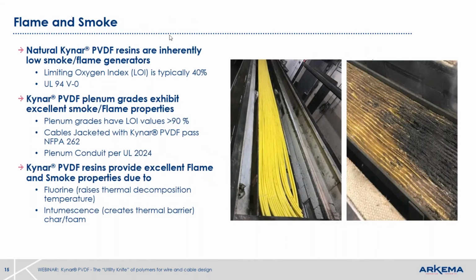Smoke and flame resistance. PVDF is inherently smoke and flame resistant. The limiting oxygen index value for unadulterated PVDF is around 40. That means you need 40% oxygen in the atmosphere to get it to ignite. I think the atmosphere is around 20-some%. So PVDF on its own is very, very good for smoke and flame resistance. And the UL 94 rating is V0.